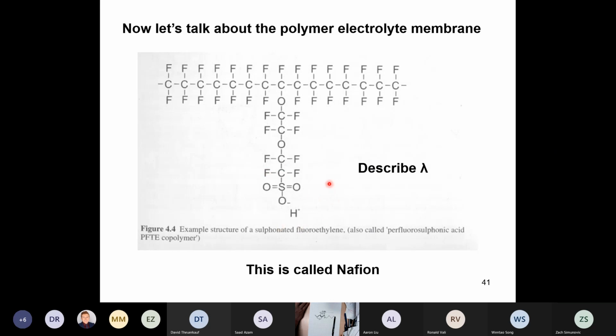Okay, and these Nafion polymers would typically operate well between about lambda equals 3 and 14 or something like that. So if lambda gets really small, the protons can't hop from sulfonate to sulfonate. There's nothing in between to help them move along. So it's called perfluorosulfonic acid PTFE copolymer, and here's the fluorosulfonic acid part. An acid will give you good proton conductivity for sure, good ionic conductivity, and this membrane will as well if it's somewhat wet.